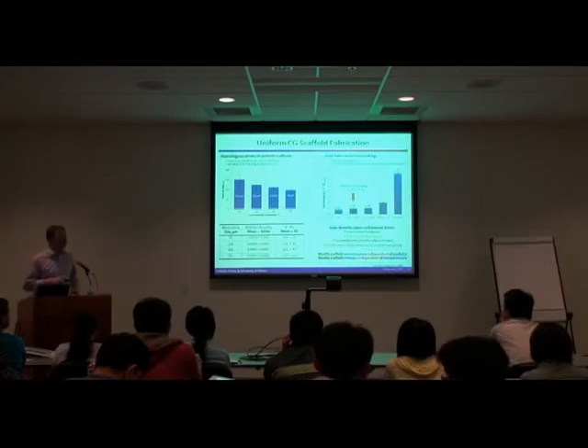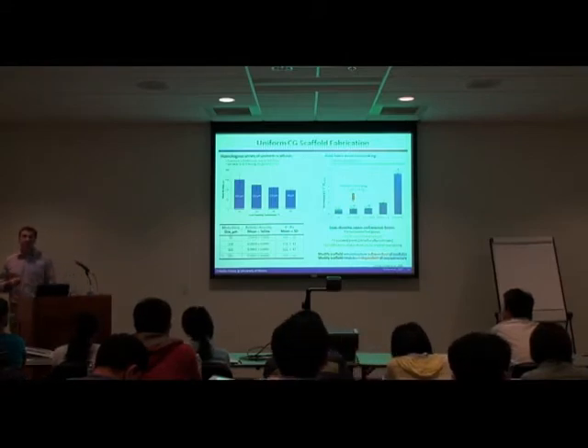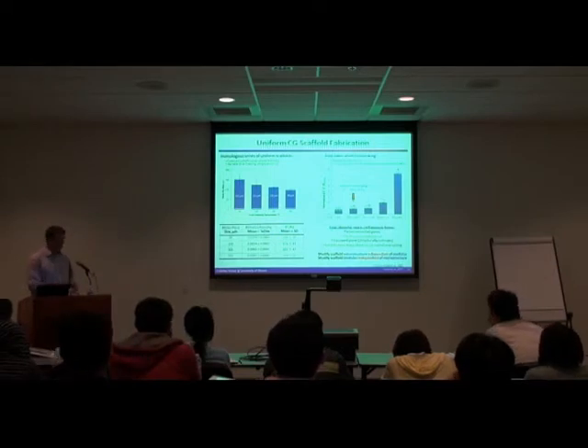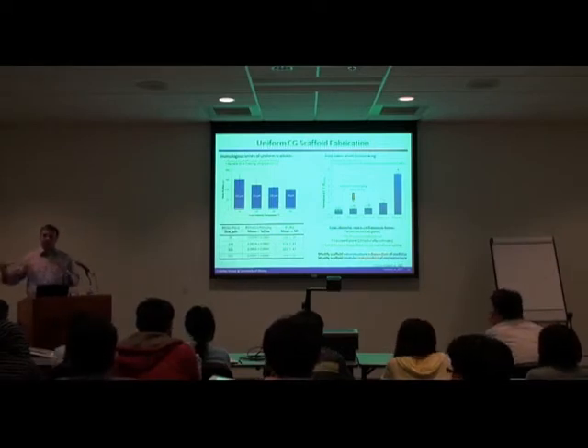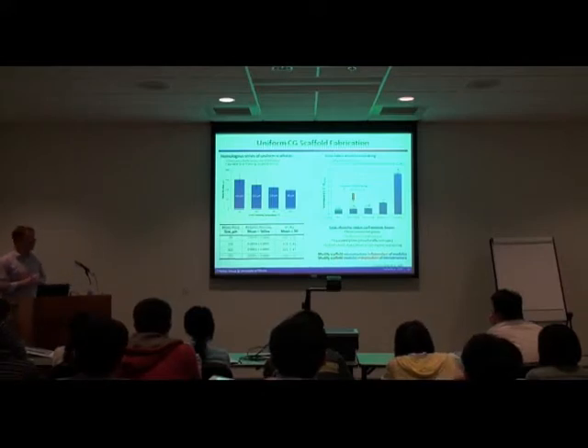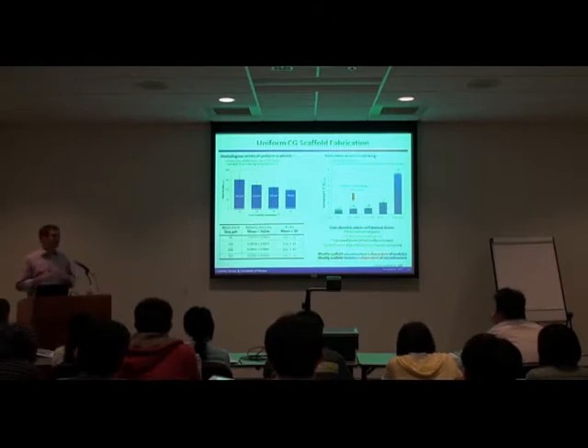And so what we try to do is create a homologous series of biomaterials. And the concept behind a homologous series of biomaterials is that you want to take one biomaterial and make a number of variants of it where you're changing only one property, and you're keeping everything else constant. And the idea behind why that is important is, especially as you start to try to make quantitative measurements of cell behaviors, or if you're trying to optimize a material for a particular application, it's very useful to know exactly what the structure-function relationships are that you're measuring.